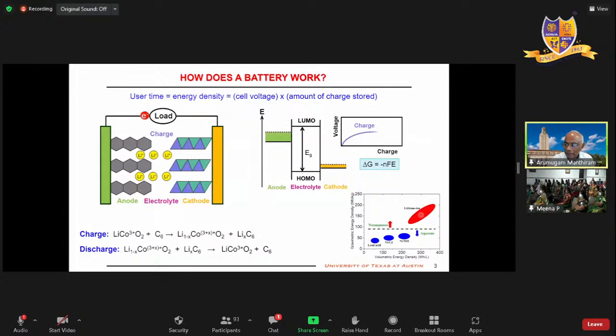When you go to lithium-ion batteries, water is an enemy. You have to use non-aqueous, water-free electrolyte; even parts per million levels of water cannot be present in lithium-ion batteries. Because you have non-aqueous solvent, not water, the band gap of the electrolyte is widened. So I'm able to keep the cathode energy as low as possible and the anode energy as high as possible, but not more than 4.2 volt. But that is a lot better, double the voltage compared to any of these batteries. So you can see here, voltage is doubled. That means use time is doubled if the amount of charge stored is assumed to be similar. So that's why all the action is on lithium-ion batteries.